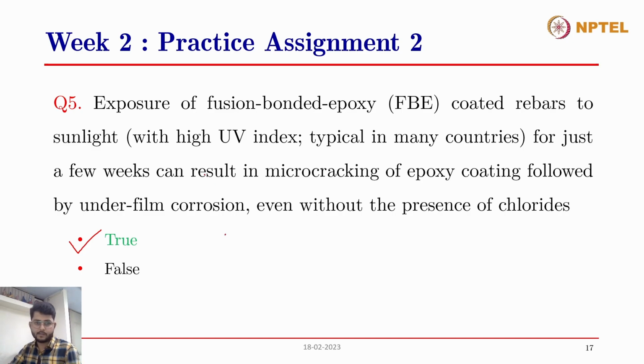Last time also we had discussed regarding crevice corrosion. So first of all, whenever these fusion bonded epoxy coated rebars are exposed to direct sunlight, the UV radiation from the sunlight causes micro cracking of this epoxy coating, and this epoxy coating becomes brittle. Since this micro cracking will expose the steel covered inside the epoxy coating, that will accelerate the corrosion process.